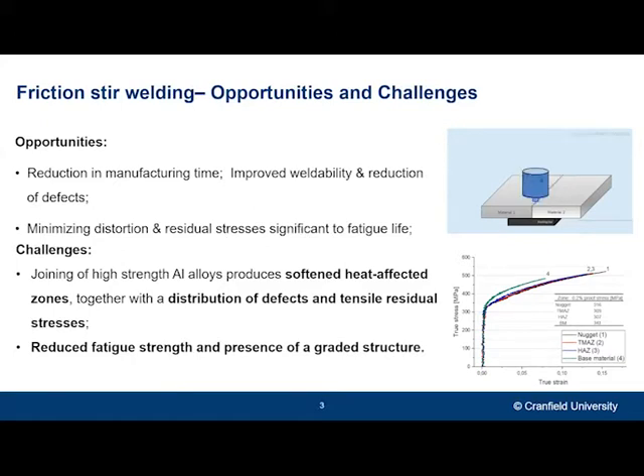In all welding processes that aim to join high-strength aluminium alloys, friction stir welding is also prone to a distribution of defects, tensile residual stresses, and softened heat-affected zones. The softened heat-affected zones mean that different regions of the welds will have different mechanical properties compared to the base material. You can see that in this plot at the bottom, where the stress and strain curves were obtained using DIC, or digital image correlation. As you can see, there is a difference of about 30 megapascal when we compare the base material to these different weld regions. Essentially, the combination of softened zones, defects, and tensile residual stresses has been proven to reduce the fatigue strength and life when compared to the parent material.